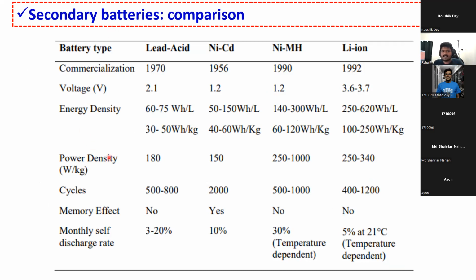So this is a comparison between the secondary batteries. And you can see that the lithium-ion batteries are at the top front of the list. Actually, lithium-ion batteries were commercialized in 1992. Sony commercialized it. You can see that we can get a nominal voltage of around 3.6 to 3.7 from a single lithium-ion cell. The energy density and power density are very high for the lithium-ion battery, as well as a very long cycle life, as well as the self-discharge rate.